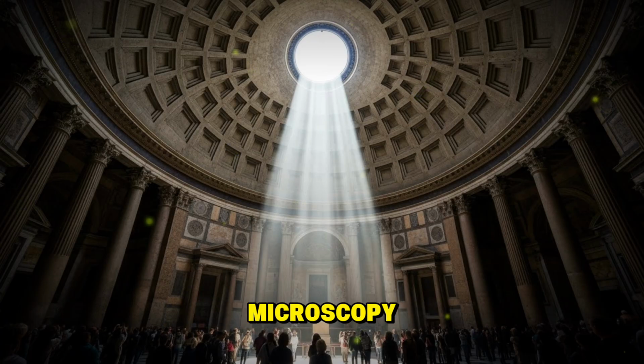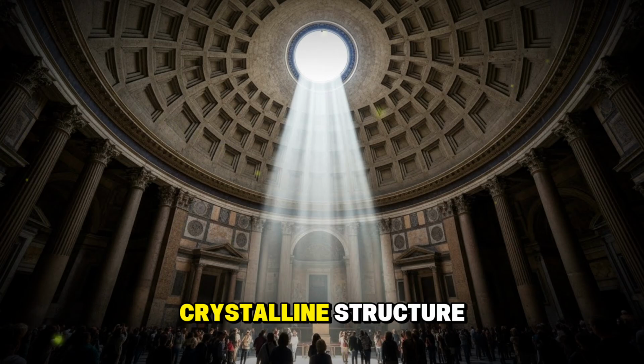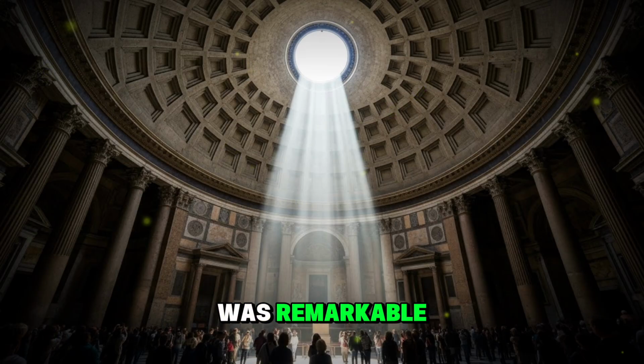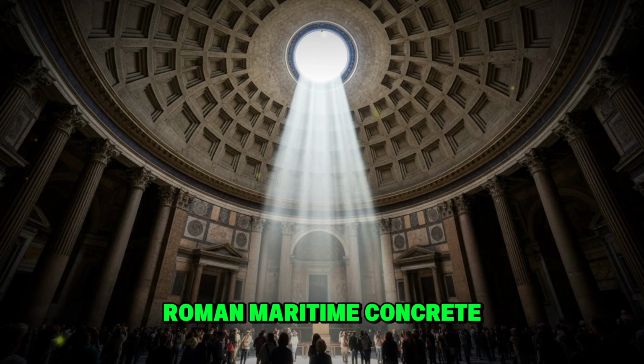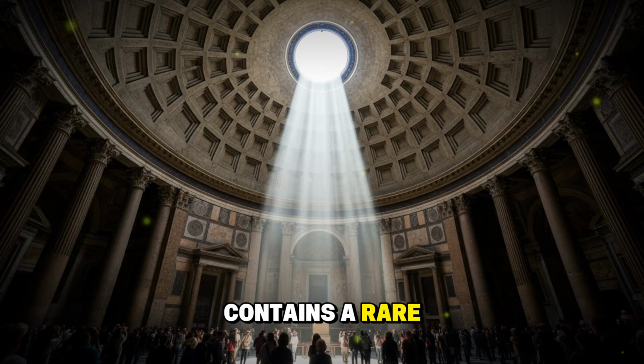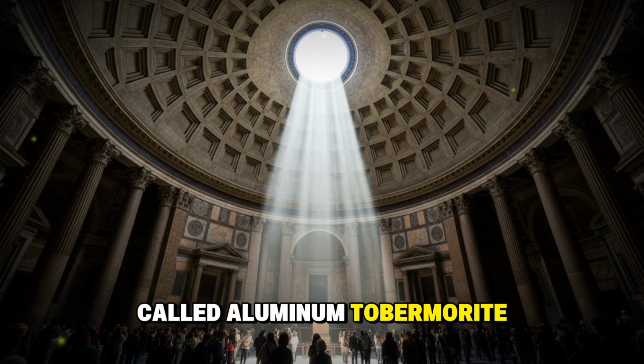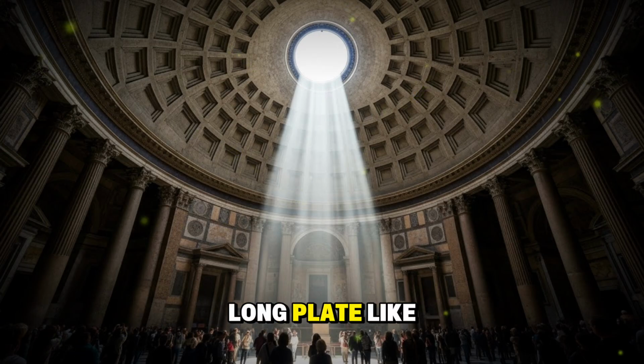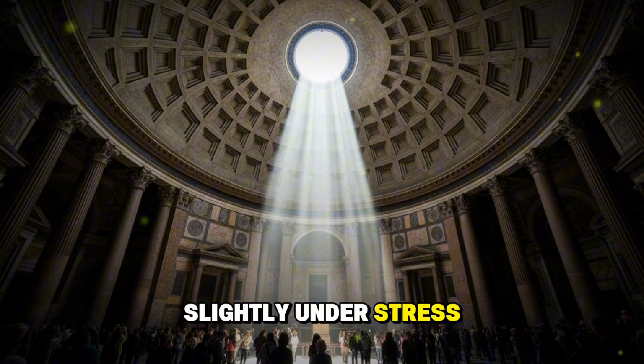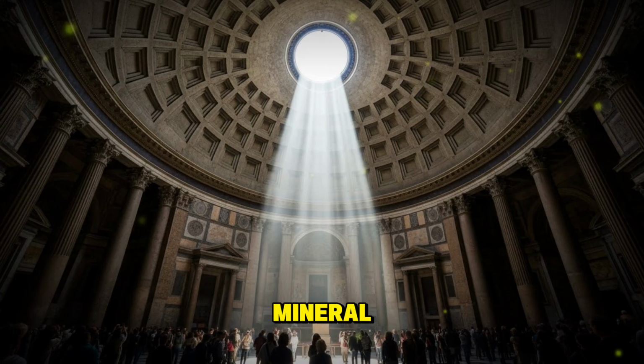Using scanning electron microscopy, X-ray diffraction, and Raman spectroscopy, she and her team mapped the crystalline structure of the ancient concrete at extremely high resolution. What they found was remarkable. Roman maritime concrete contains a rare mineral called aluminum tobermorite. This mineral has long plate-like crystals that allow the material to bend slightly under stress rather than crack. Modern concrete does not contain this mineral.